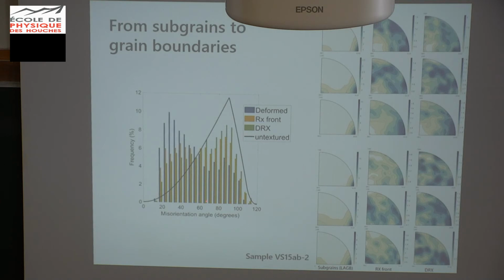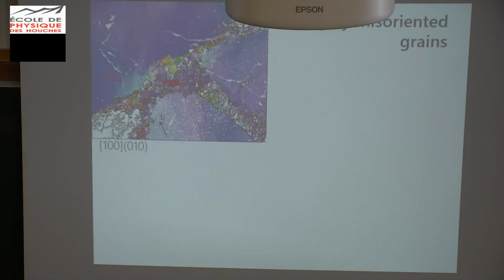And also when looking into the misorientation angle, one might expect that for the recrystallization front that puts the new grains in contact with the parent grains, the misorientation angle should be close or not far away from 15 degrees, but you can see that the probability of finding a misorientation angle of 40 is about the same as finding a misorientation of 90. It is surprising.